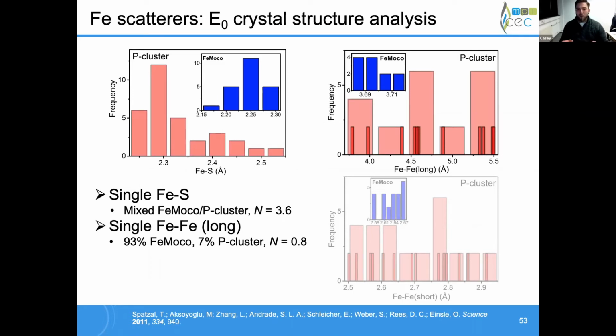This is a similar story for everything, FeMoco versus P cluster. If we look at our long iron-iron distances, FeMoco has very well conserved long iron-iron distances that come from the scattering between irons across each other on the cofactor. And if we look at the P cluster, there are also a number of long iron-iron scatterers, but they're really spread apart in terms of total distance. And so most of what we can fit is only going to be this tight bundle here. It'll have maybe a small amount of P cluster contribution, but it's a pretty strong indicator of what's going on at the FeMoco cluster.